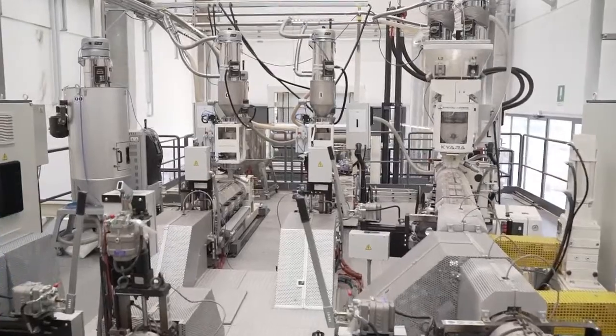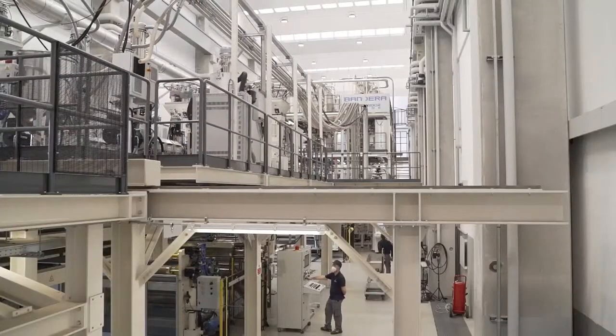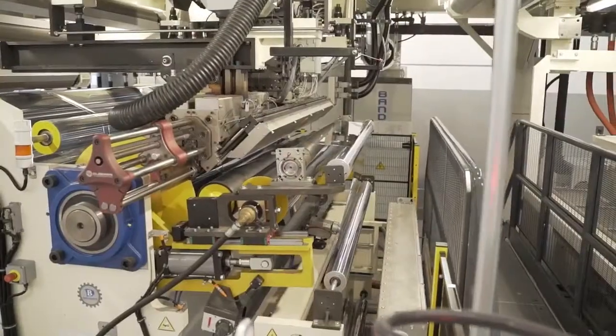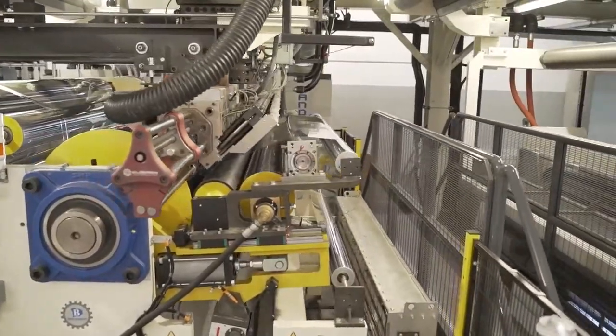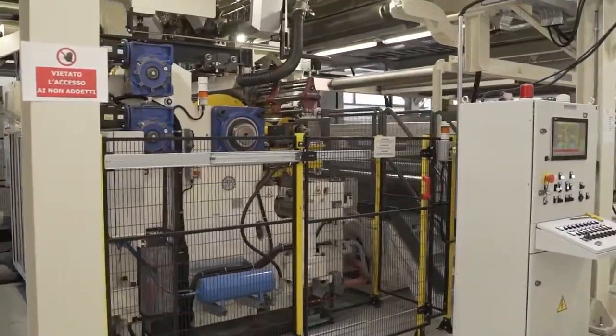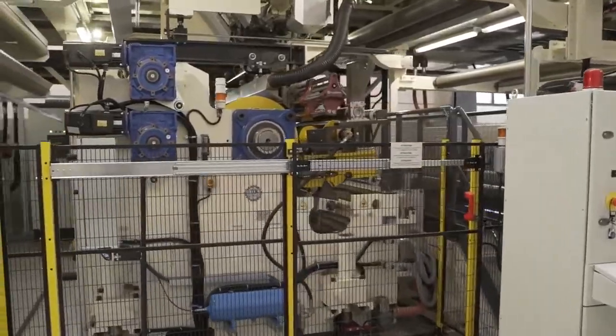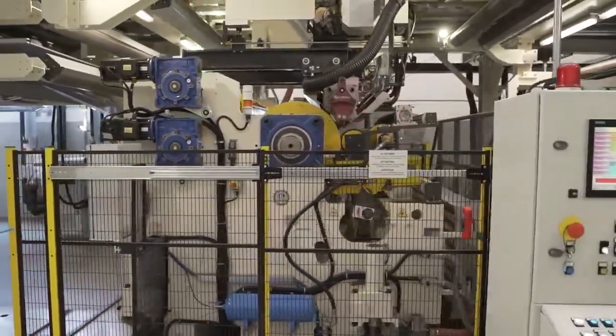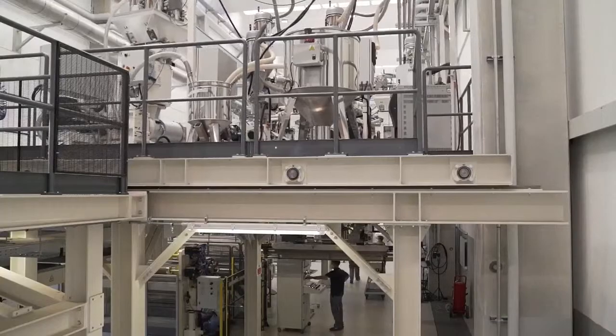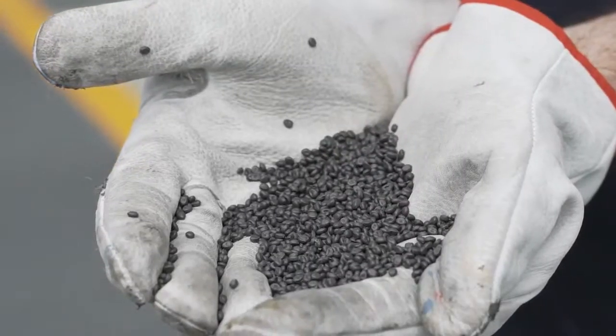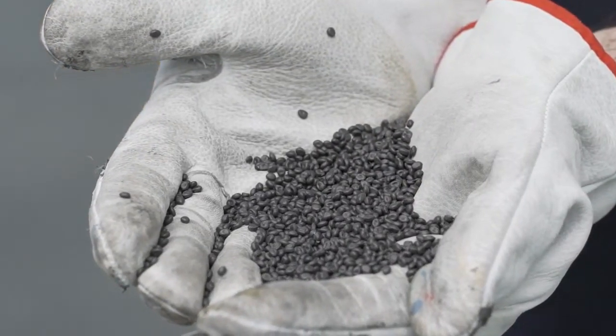Extrusion coating lines offer high flexibility in the production of this structure, thus favoring barrier layer asymmetry and optimizing the use of tie resin and EVOH that significantly affect cups' overall cost. By means of extrusion coating, Bandera can use high quantities of recycled material and thermoforming scraps in the substrate without any viscosity fluctuation issue, as opposed to the common co-extrusion in one die only.